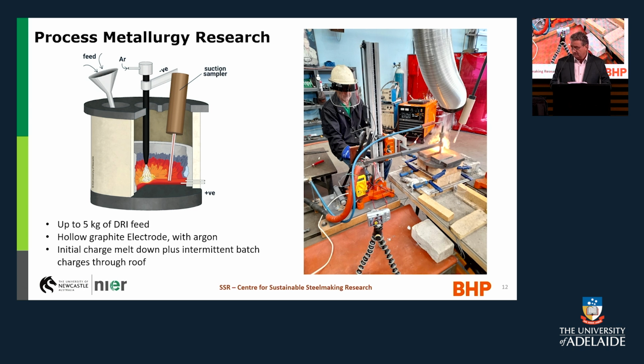So of course with electrode smelting, because you're heating in this mode of electrode centre to sidewall, the temperature gradients we have in the smelting reactor are really very large, laterally from centre to sidewall and also from top to bottom. Okay, so that's what we try to deal with. And being a pyrometallurgist, we always say, oh, what temperature did you do it at? And I say, well, mate, it's just a reactor full of very big temperature gradients. And so to talk about a single temperature is really a bit of a false argument. So you're dealing with a smelting system that covers a very wide range of temperature.